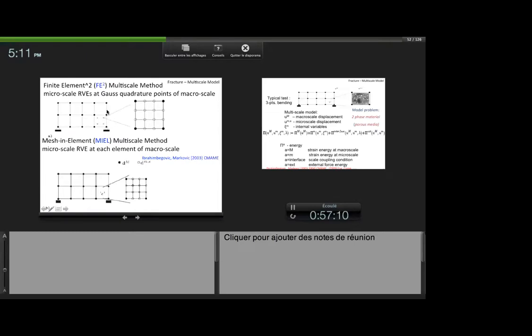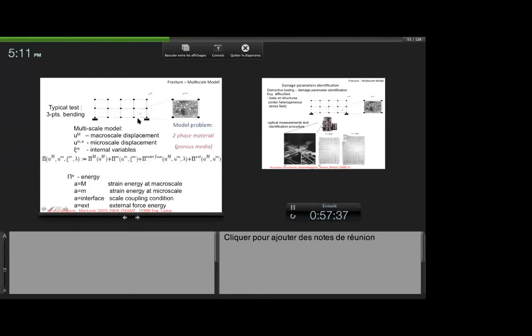Well, we didn't want to do this homogenization story, what they call FE squared, although our stuff is frankly closer to FE squared than theirs. We call it MIEL. Miel in French is honey. Actually a colleague of mine, Herman Matthies, called it MIEL. Mesh in element, multiscale method. So you take a macroscale formulation of this specimen, and then at one macro element, you build a mesh of these micro elements. You're going to take a different coordinate to integrate that. More realistically, it's like this. Basically, take a macro element, you fill it in with the microstructure.